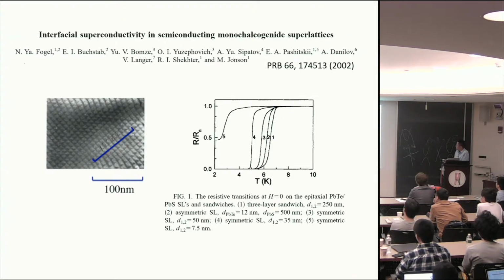Because these different materials have slightly different lattice constants, at the interface between two different materials, the system self-organizes into an array of dislocations. Basically, dislocation is a way for the system to relax the strain and match the lattice constant as much as it can. And what ends up happening is that at the interface, there's a periodic array of these dislocations.